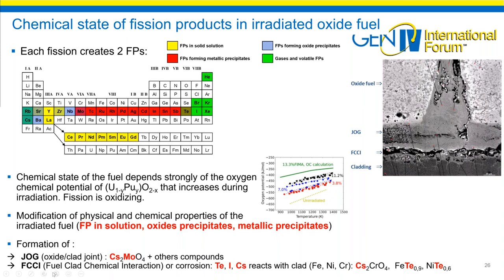We can have also a fuel clad chemical interaction or corrosion, and it's a reaction between some fission products, tellurium, iodine, cesium, that reacts with the components of the cladding, mainly iron, nickel, and chromium, in order to produce the cesium chromate, the iron telluride, and also nickel telluride. So next slide, please.